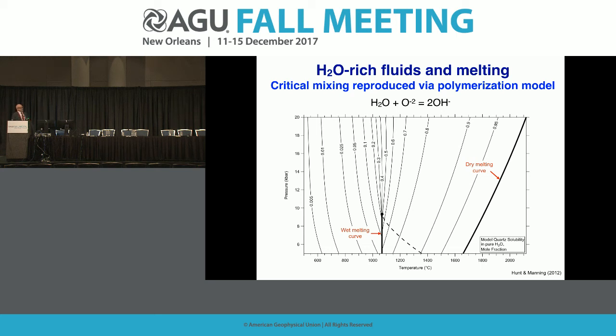And when we do this, we predict the melting curve, which you can see here. We predict that it moves up along this line here, and then there's another line here, a dashed line called the critical curve, which is where liquid and vapor meet and join and become one solution. And we see that we predict an upper critical endpoint in this thermodynamic model, which knows nothing about where anybody has ever measured quartz melting in the presence of H2O.